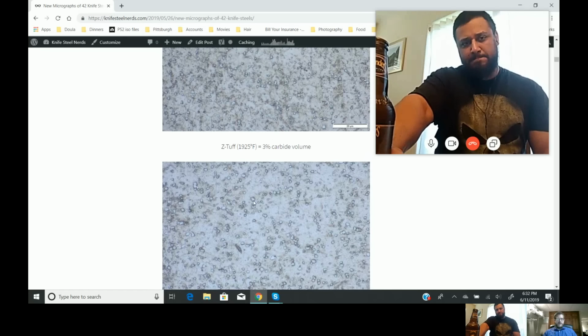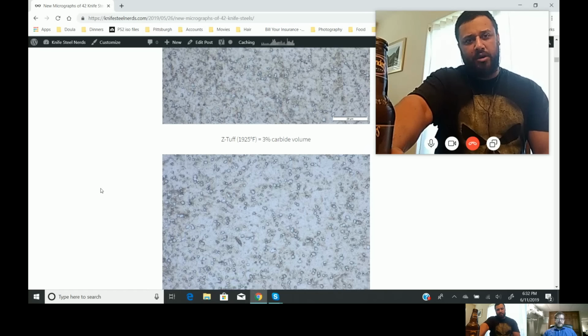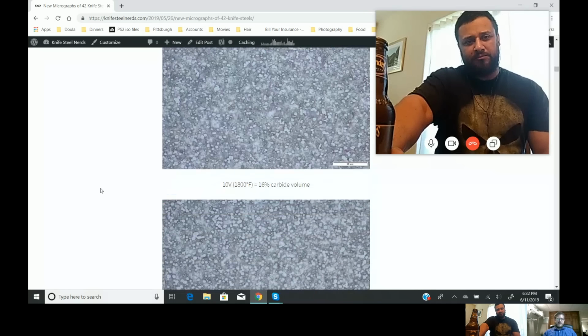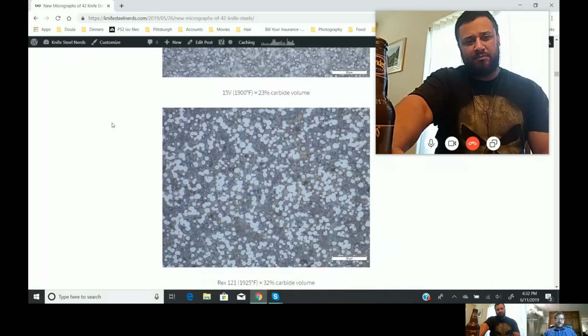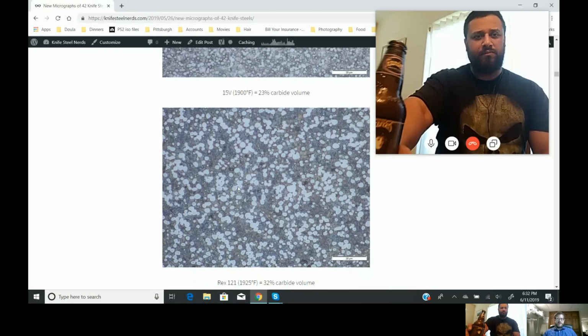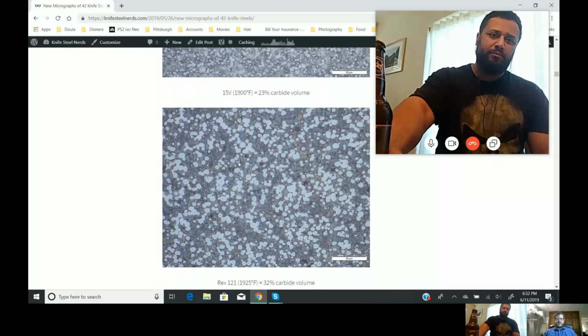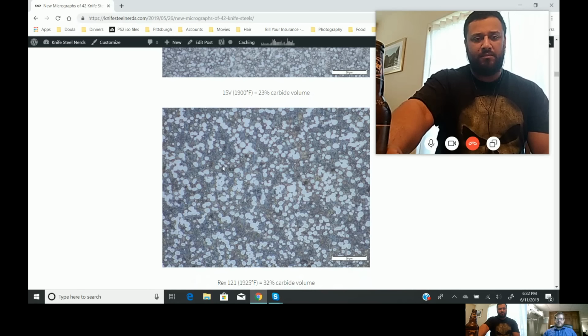Yeah, I'm pointing at one with my mouse. Okay. In Rex 121, you can't miss them. They're usually like the white particles with a darker matrix behind it. Different steels etch a little differently, but you can tell what the carbides are after you've looked at enough of these. And yeah, they're very hard particles, and they contribute to wear resistance.